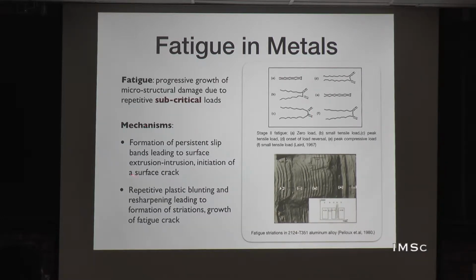So this is initiation related. This is what is happening when a fatigue crack has formed and how it grows. As engineers, we cannot say that there would not be a crack while your flight is taking off, because it's virtually not possible to have any material which has no inherent defect. The question is, if you have a starting defect, how it grows during the number of cycles you expect to operate without any incident, that should be accountable.